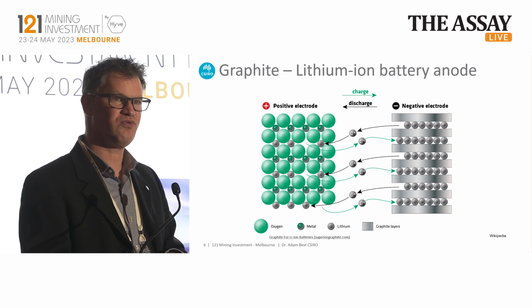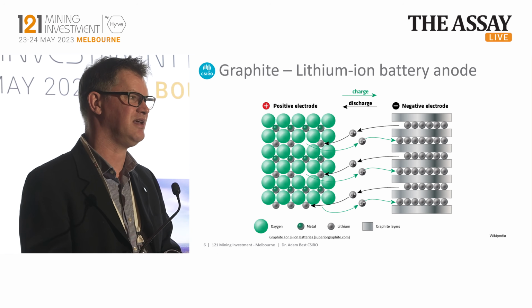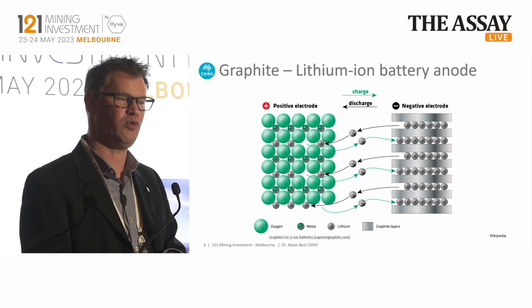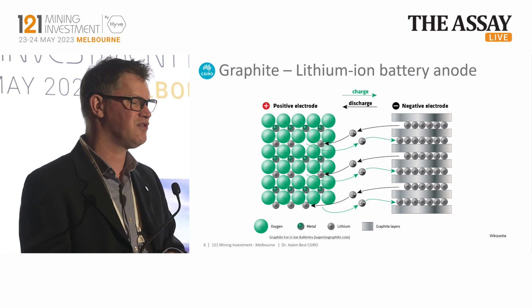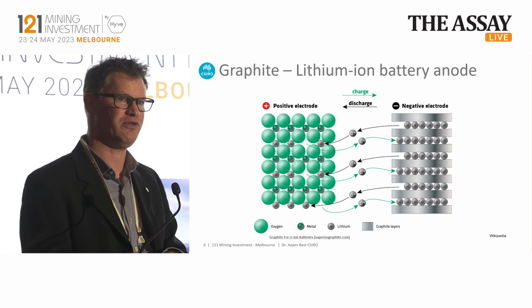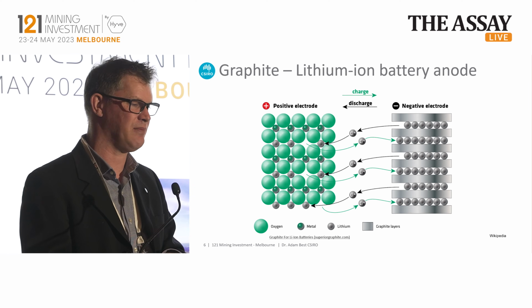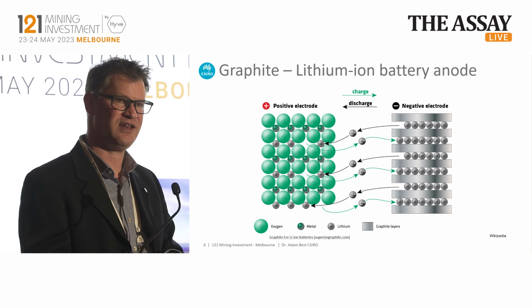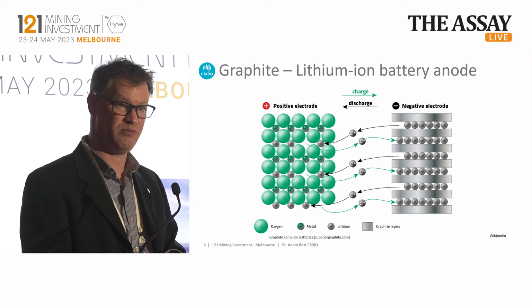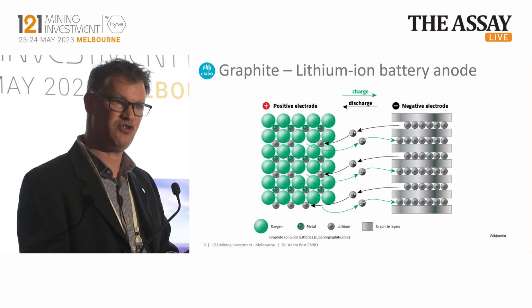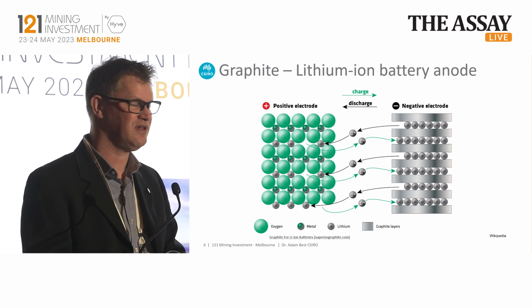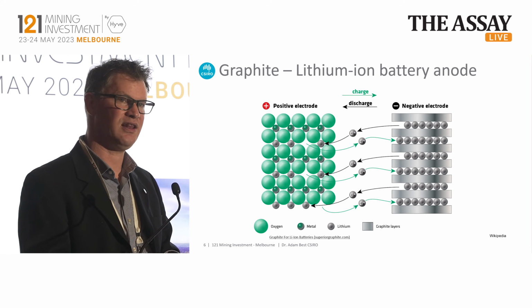So the real reason we love graphite is that it has what we call a high specific capacity, i.e. the amount of energy it can store per unit mass. And this is 365 milliamp hours per gram. So 365 milliamp hours of capacity per gram of material. This is in excess of most other commercial materials. The only two materials that compete with this are silicon and lithium metal.